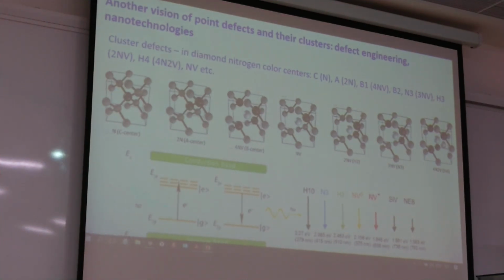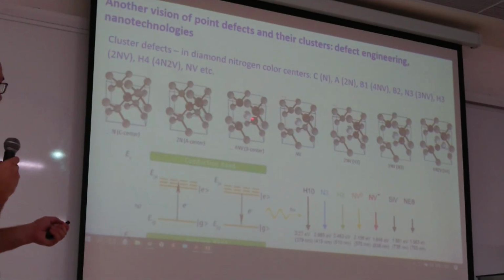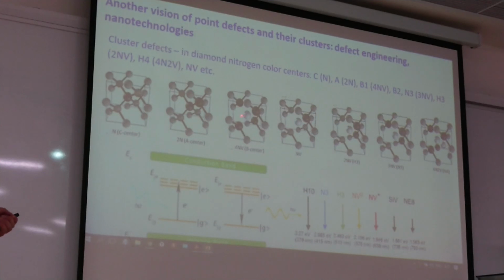For example, in natural diamonds or even synthetic ones, there are big clusters of defects. You can see here the carbon atoms of the diamond lattice, these are gray circles, and here we have one nitrogen introduced in the lattice, black one, two nitrogen atoms, the double center, four nitrogen atoms with vacancy in the center, and one nitrogen atom and vacancy center, NV center, nitrogen vacancy, and so on. So there is a big variety of defects, even in diamond, with its extra rigid lattice.